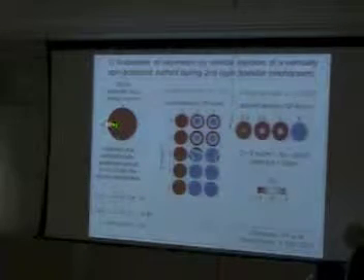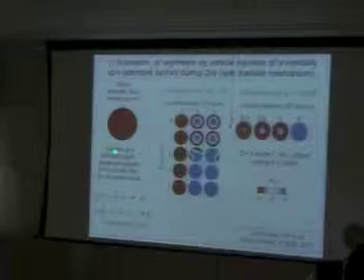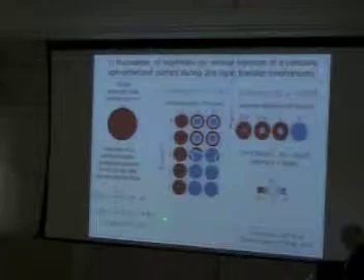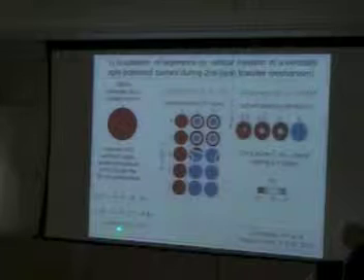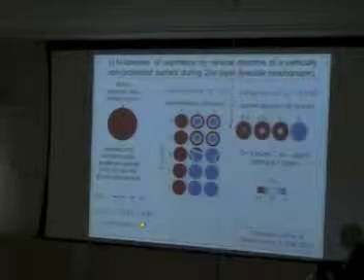We tested several mechanisms of nucleation. This one is injecting a spin polarized current, a vertical spin polarized current, into this central circle of the disk. This spin polarized current has a vertical polarization, and so we simply simulate the dynamics of the system by introducing the usual spin transfer torque that we have seen several times this morning, and introducing the polarization of the injected current, which can be injected from a magnetic junction, and alpha is the damping coefficient.